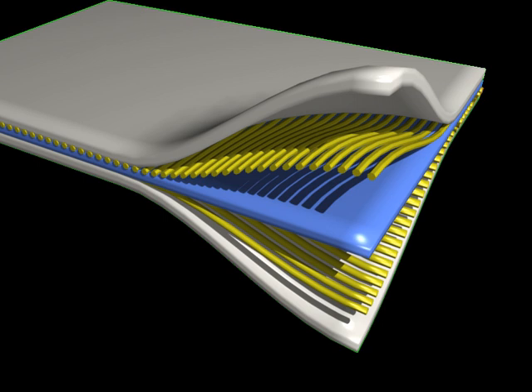This process is generally performed at both elevated pressure and elevated temperature. The use of elevated pressure facilitates a high fiber volume fraction and low void content for maximum structural efficiency.